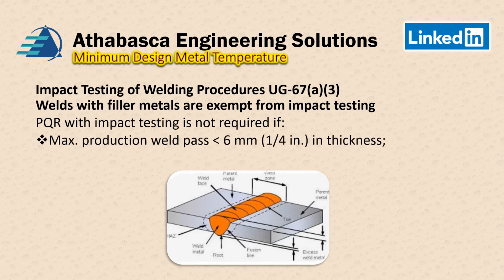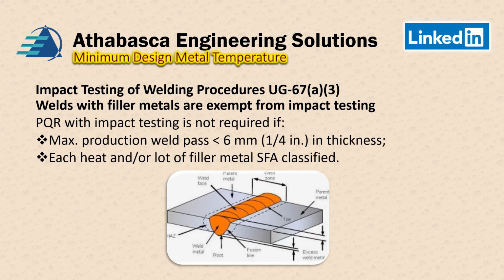If the maximum production weld pass is less than 6 millimeters or a quarter inch in thickness. And the second criterion is if each heat or a lot or combination thereof follows an SFA classification, and it's been impact tested that way.